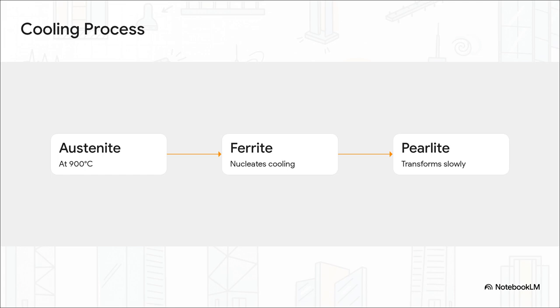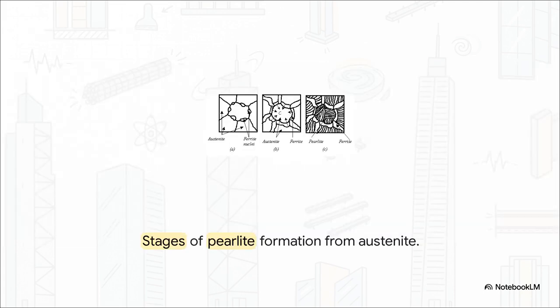As it begins to cool into a two-phase field, we hit Step 2. Ferrite starts to nucleate, forming tiny crystals right around the boundaries of the austenite grains. Because ferrite simply can't hold much carbon, that carbon diffuses away into the remaining austenite. Finally, in Step 3, as we cool all the way down to room temperature, that remaining carbon-rich austenite transforms completely into pearlite. We can picture this beautiful microscopic transformation happening in 3 distinct stages.